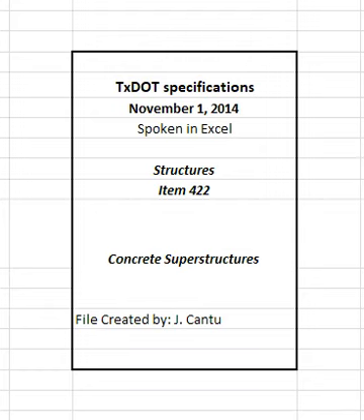4.1.2 Longitudinal screeding of bridge slabs. Place a longitudinal screed directly on previously placed concrete slabs to check and grade an adjacent slab only after the previously placed slab has aged at least 24 hours. Place and screed the concrete after the previously placed slabs have aged at least 48 hours. Maintain curing of the previously placed slabs during placement.